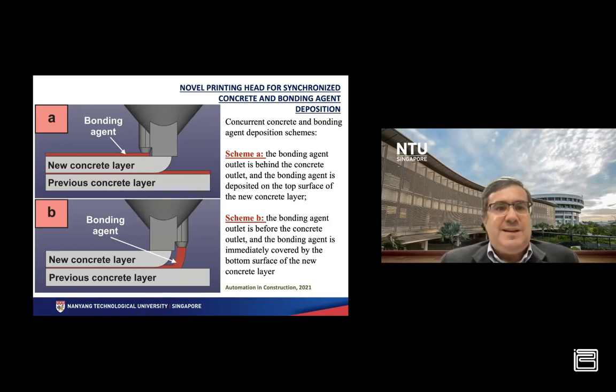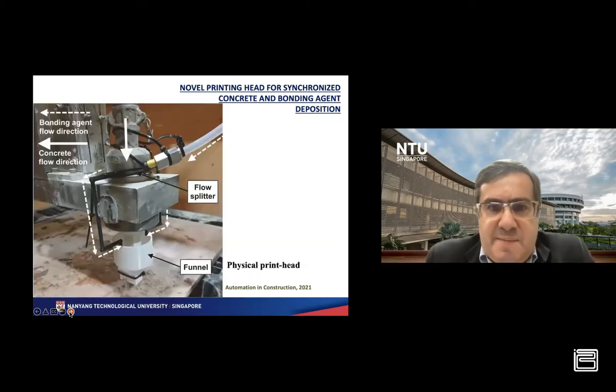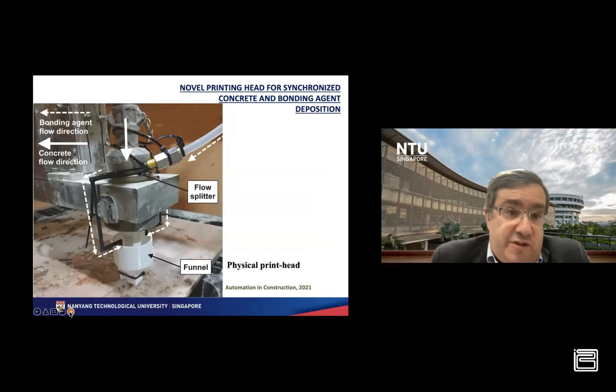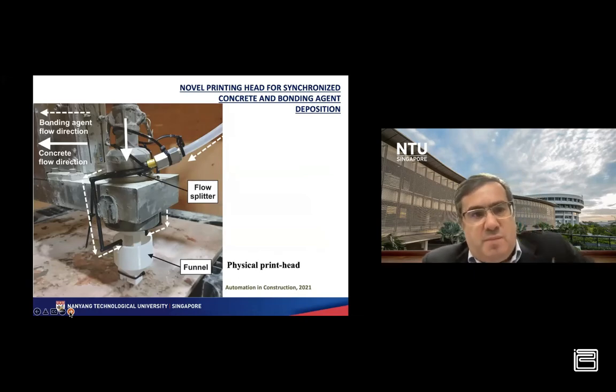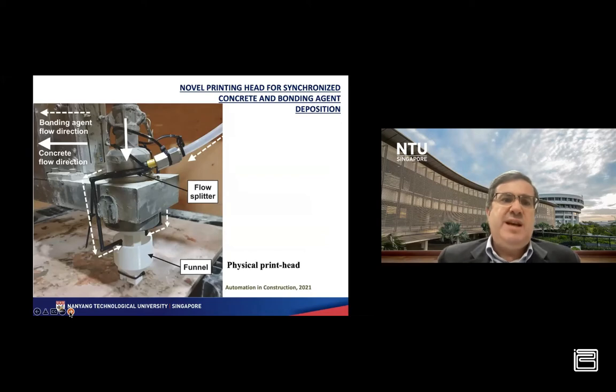So we need to decide about the best operation mode, depending, first of all, on the characteristics of the bonding agent and also on the geometry of the part to be printed. This is an image showing the physical printing head with the two operation modes, as I mentioned. But we had also another problem related to extrusion of the bonding agent material, which was related to the distribution of the bonding material at the interface between the two concrete layers due to the high viscosity of the bonding agent.